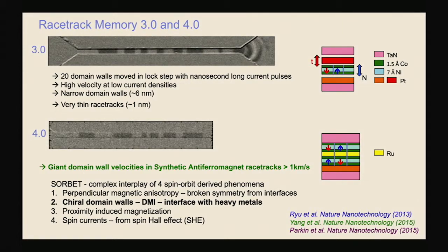And we can do that, as you can see down below, by building a structure of 2 racetracks, one on top of the other, coupled through an ultra-thin layer of ruthenium, which is, again, something I discovered 30 years ago, which is that you see an oscillatory, long-range coupling through ruthenium. And for thin layers in the range of 2 to 7 angstroms, it's antiferromagnetic.